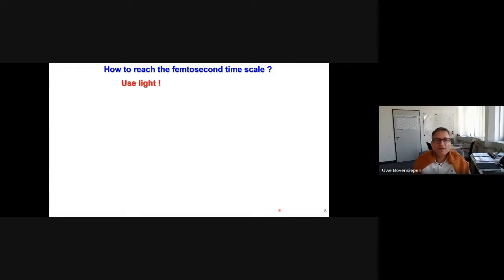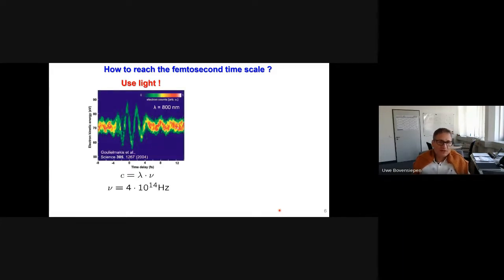Now, an important question is, how do we reach this femtosecond timescale if we want to do these experiments? And there's a simple answer: use light. And just to emphasize this statement, I show here work by Ferenc Krausz and co-workers from a couple of years ago, where they could show in a time-resolved experiment, in fact, this was an attosecond time-resolved experiment, the temporal variation of the electric field in an 800 nanometer laser pulse. So if we have 800 nanometers, which we can measure by a spectrometer, we can simply calculate by the known velocity of light that the frequency is 4 times 10 to the 14 hertz.